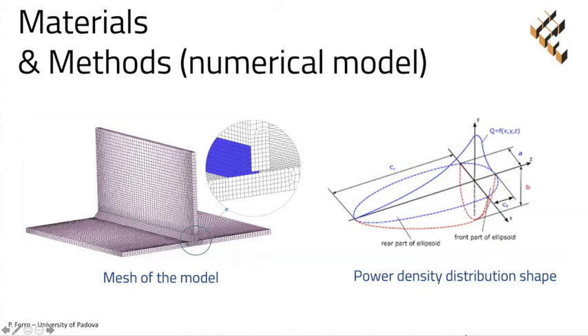The heat source was modeled using a double ellipsoid power density distribution function proposed by Goldak, where its parameters are calibrated by using experiments. Radiative heat loss using the Stefan-Boltzmann law and convective heat loss were applied at the boundary of the plates to be joined. In the mechanical computation, the weldment was considered isostatically clamped.